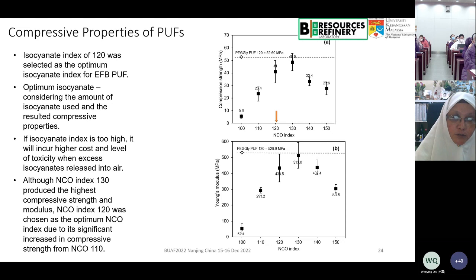And for the Young's modulus also, it increases up to 130, then it starts to decrease. But the steep part is from 110 to 120. For that reason, we choose 120. But it depends on the end use. If you're talking about strength, then you pick 120. But if we are talking about biodegradability and how much water absorption and so on, maybe a 100 NCO index is the best.